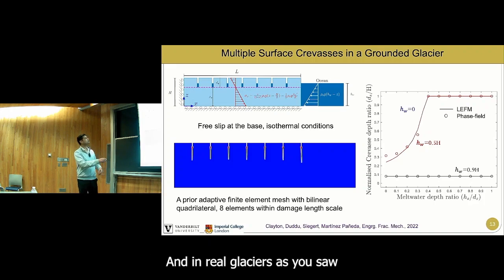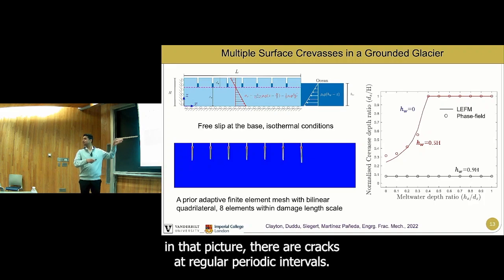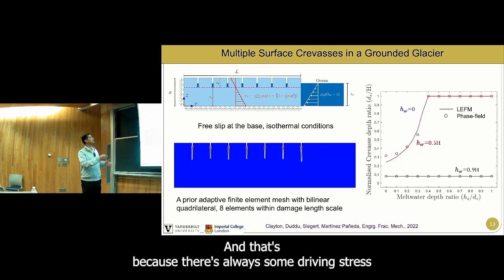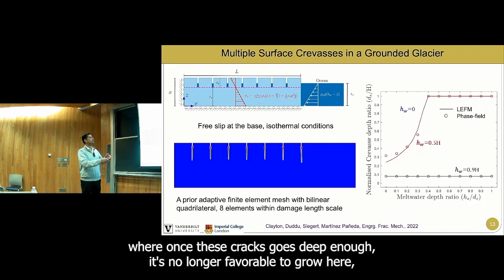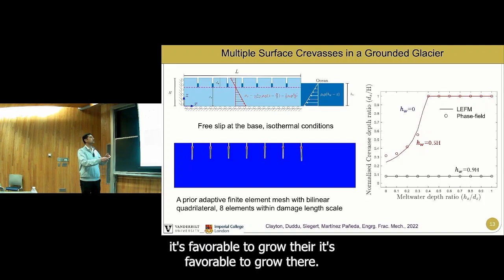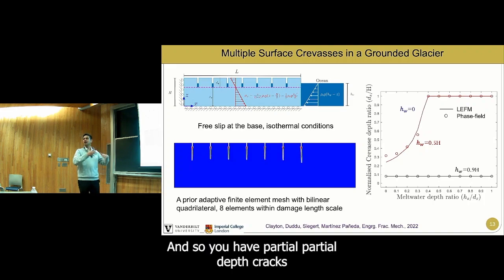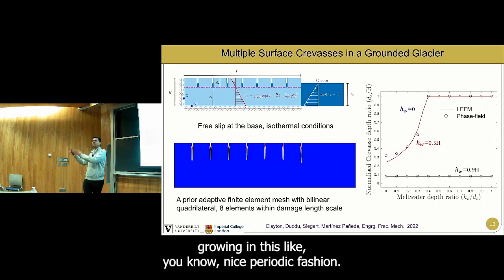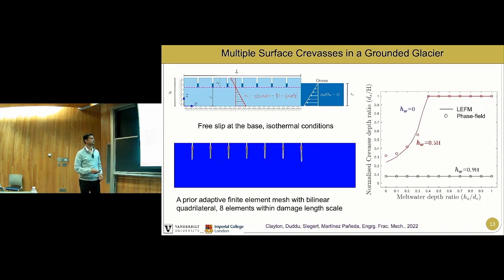And in real glaciers, as you saw in that picture, there are cracks at regular periodic intervals, right? And that's because there's always some driving stress where once this crack goes deep enough, it's no longer favorable to grow here, it's favorable to grow there. It's favorable to grow there, right? And so you have partial depth cracks growing in this nice periodic fashion.